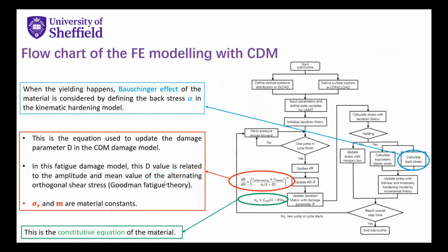Okay, let's look at the flowchart of the FE modeling with the CDM method. At first, I defined the plastic deformation in my modeling because we have the stress concentration due to inclusions, so it may have some plastic deformation in the subsurface area around these inclusions. And when the yielding happens, I also consider the Bauschinger effect of the material. Then I calculate the back stress, and I update my stress based on the kinematic hardening model here.